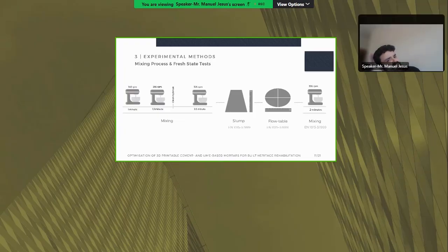Regarding the mixing process and the fresh state tests, a strict mixing protocol was followed that began with the accurate weighing of all constituents. First, the dry materials were blended in a mixer at low speed to ensure a homogeneous distribution and to prevent segregation. We then gradually added water over a 90-second period while increasing the mixer speed over time. And to guarantee the full incorporation of all the components, we paused to scrape the mixing bucket and the paddle before a final 2.5-minute mix.